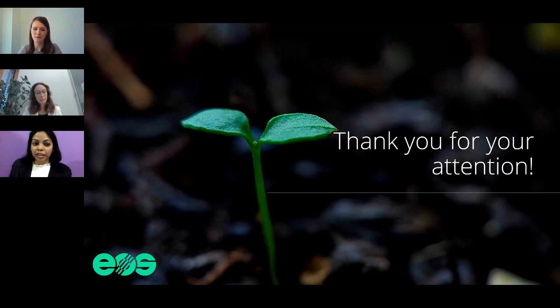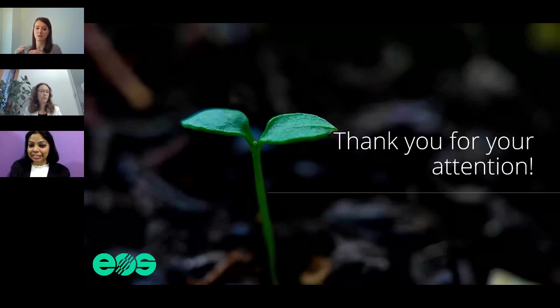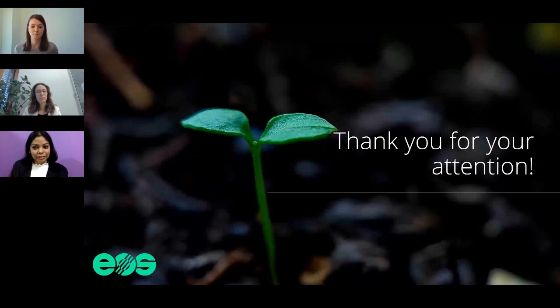Mm-hmm. And maybe to add on that, Swati, we're not talking a lot about polyamides because it's one of the main materials, like in laser sintering. But if you look at other materials like TPU, for example, there we are already really, really low with refresh rates. So when we do our development process in-house, we usually have the problem that we have to scrap enough powder out of the old job to get enough for the new one. So in certain materials, we are already at the optimum level, basically, with TPUs, for example, but there are other parts where we are not yet there, and that's the road ahead, basically.